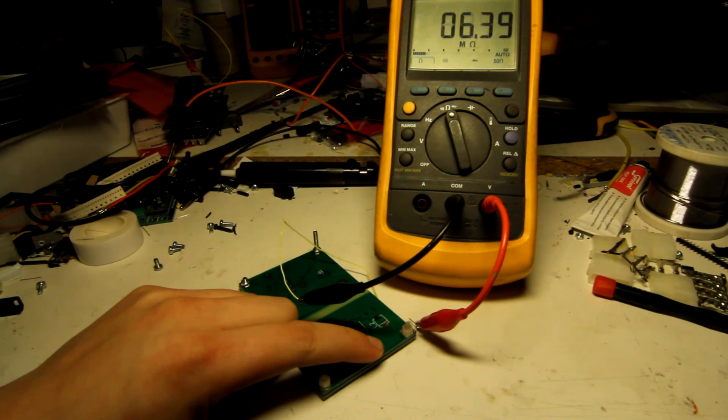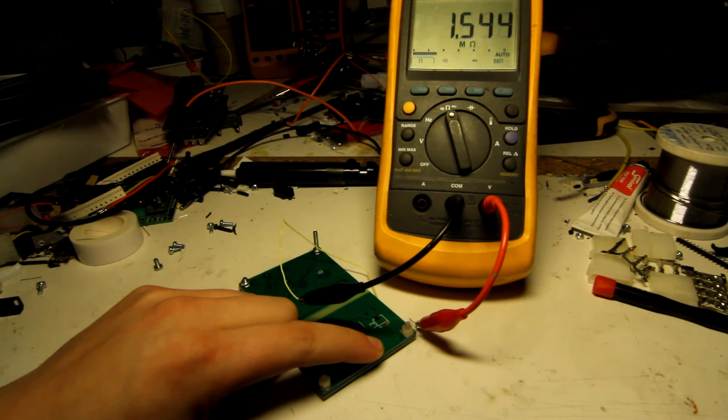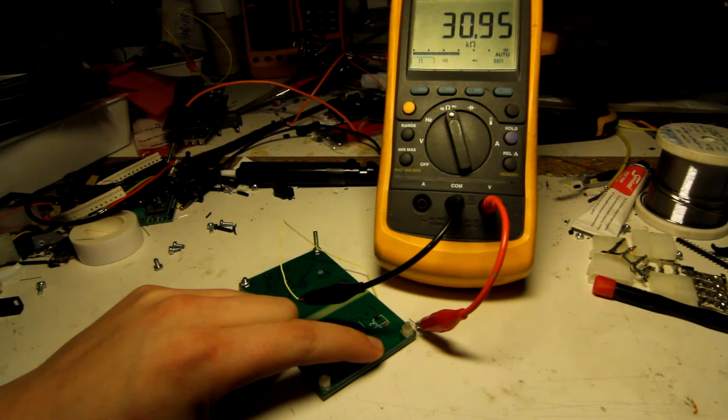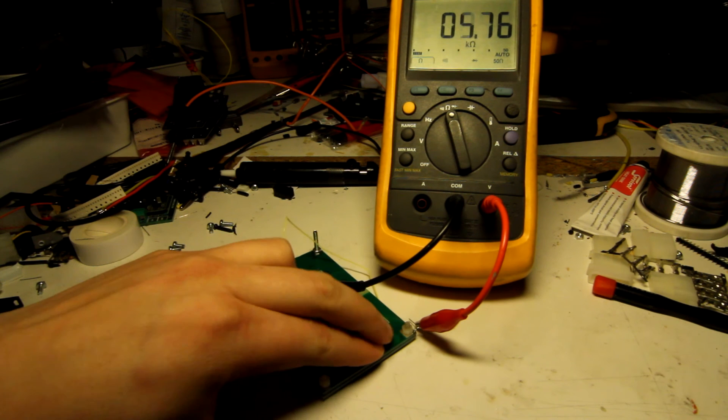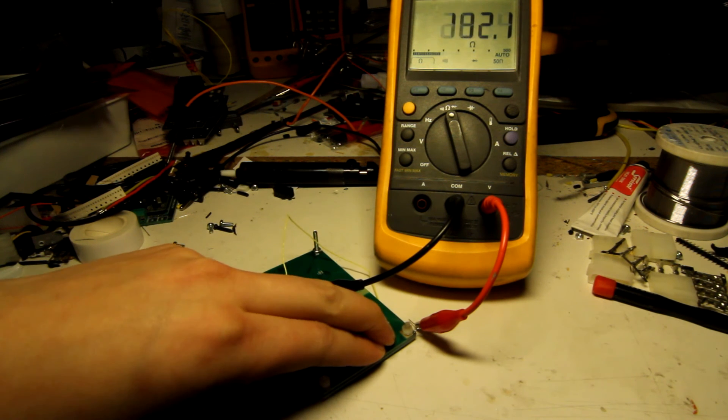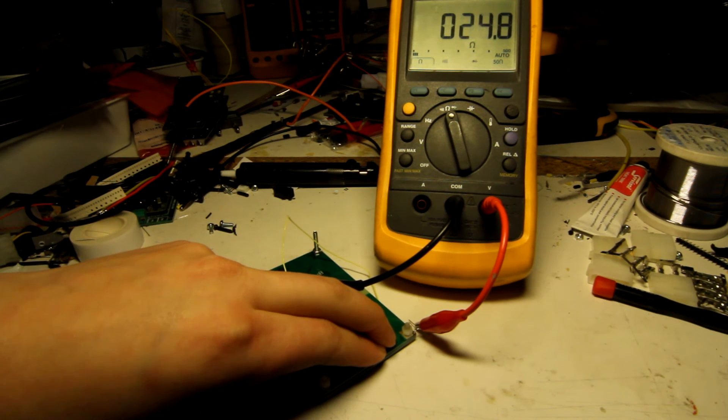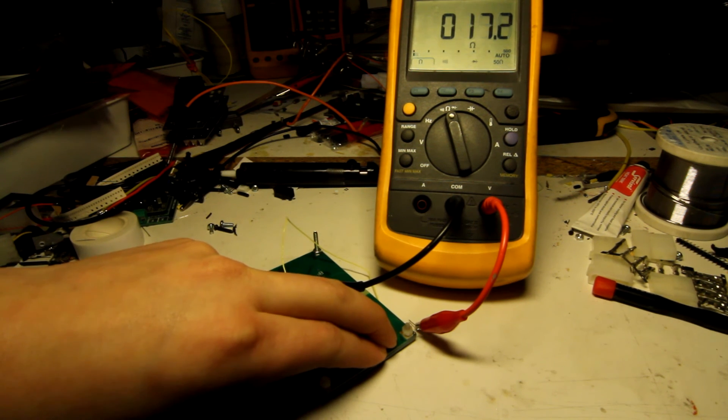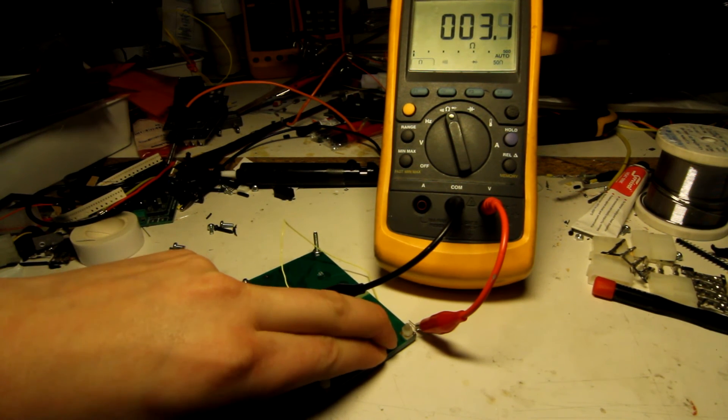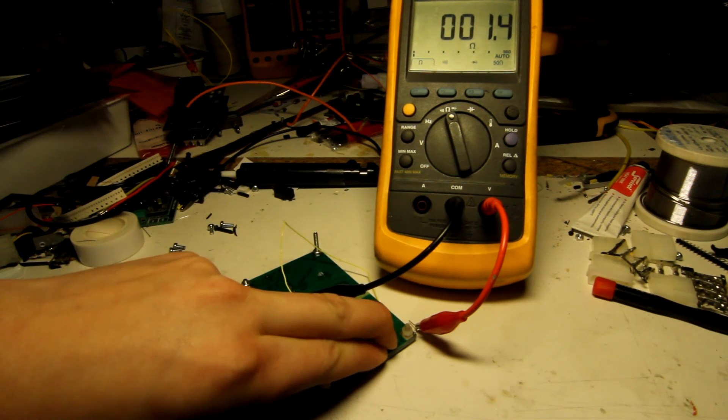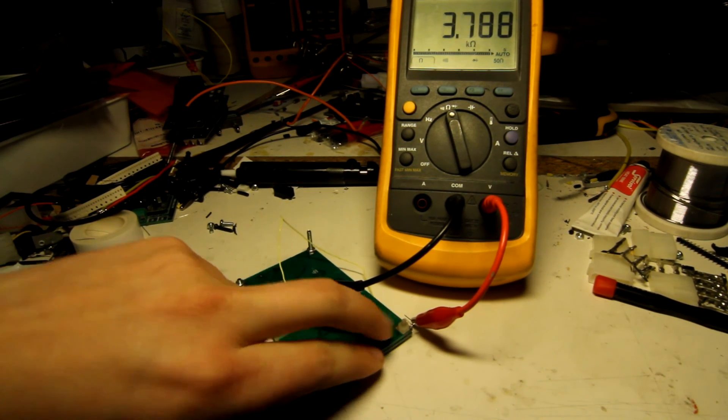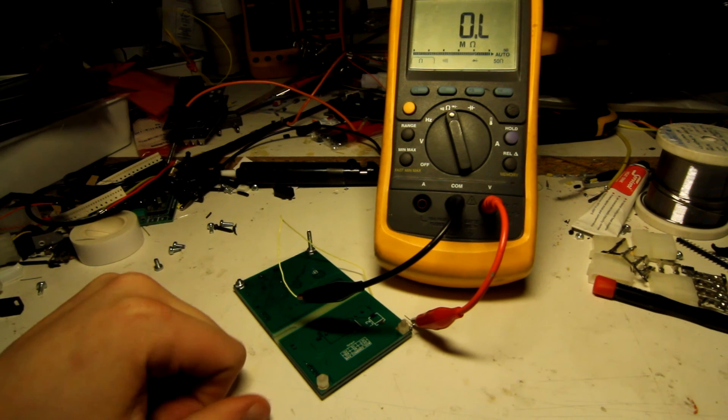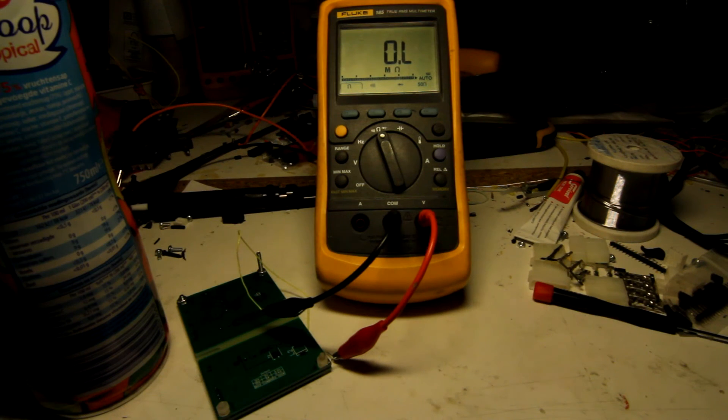And as I push down, you see, it's now a couple of megaohms. I push harder and it now goes into the kiloohm range - a couple tens of kiloohms. And if I push really hard, I can get it to go down to low ohms range. If I get really hard, I can get down to less than one and a half ohms, but that was like 20 kilograms of pressure or something.